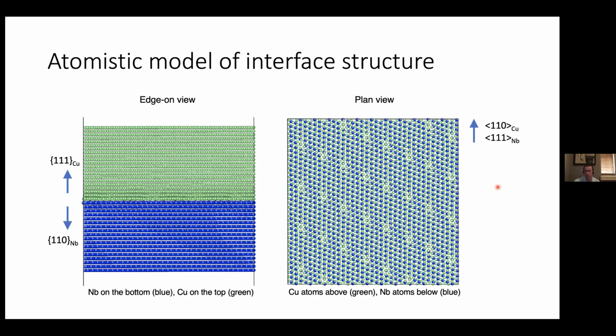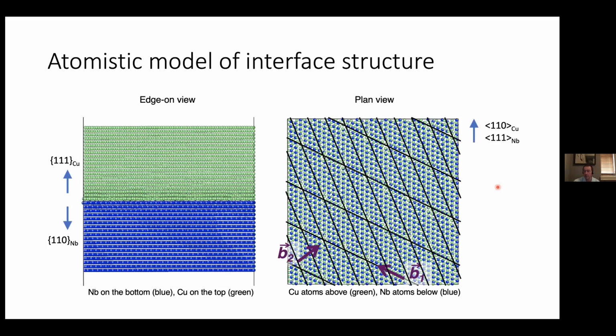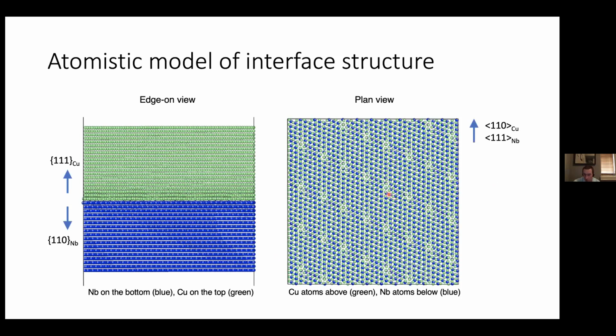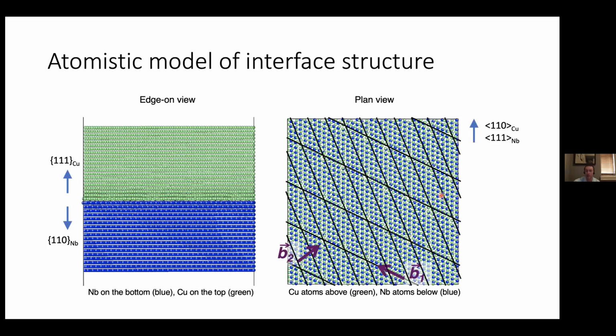So this particular interface contains two sets of dislocations. This is one set. This is the orientation of one set of dislocations. Here's the orientation of the second set of dislocations. And all those little places here where you have near perfect coincidence between a copper and a niobium atom are actually the intersections between those dislocations. So those are misfit dislocation intersections.